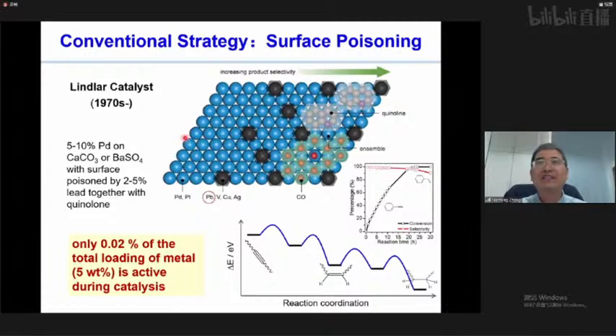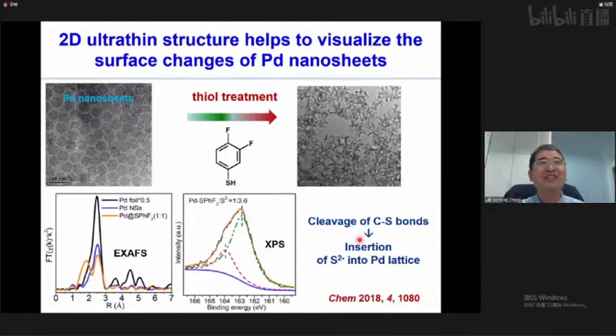In industry, they already developed an effective catalyst, which is the Lindlar catalyst. They try to poison the surface by using lead or other organic modifiers. Okay, they modify the surface, they poison the surface, they reduce the reaction rate so that they have a chance to stop the reaction at the double bond. But the disadvantage of this technique is that we need to lower the reaction rate.